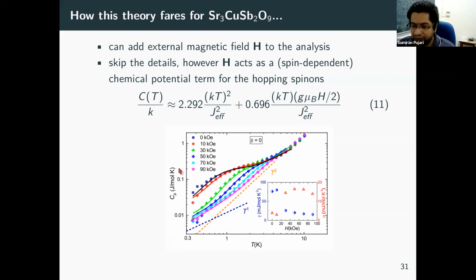So let me go through this for a minute. This is the specific heat data on this compound. Initially, when Avinash showed me the data, what he was curious about is that, for example, if you look at this green curve at 30 kilo-oersted, on a log scale, it looked quite like a T squared. And he was wondering, where could a T squared come from if there is no ordering in the sample? But it naturally struck me that T squared would come from Dirac spinons, these linearly dispersing spinons. So I thought maybe that explains it.